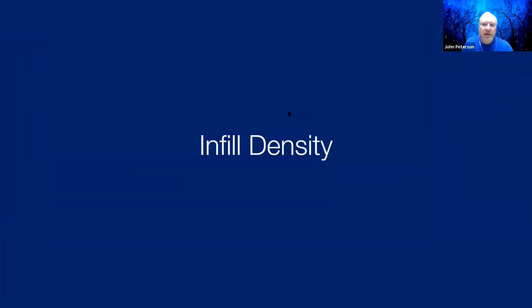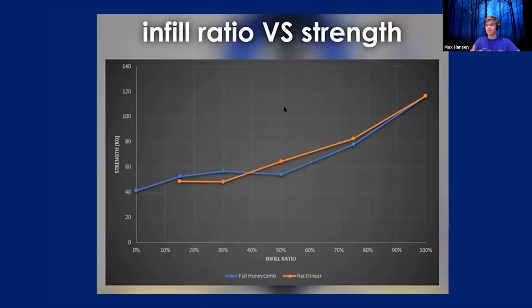And then we can look at some infill density, which is the percentage of the part that is infill. So as you can see here, he just ended up looking at a full honeycomb pattern and a rectilinear pattern. And as they go up, much as you would expect, as the infill percentage goes up, so does the strength. But it's important to see that down here at like the 20 to 40 range, the honeycomb is actually stronger than the rectilinear, and then that changes right when you hit about 40%, and the rectilinear ends up being stronger up in that range.